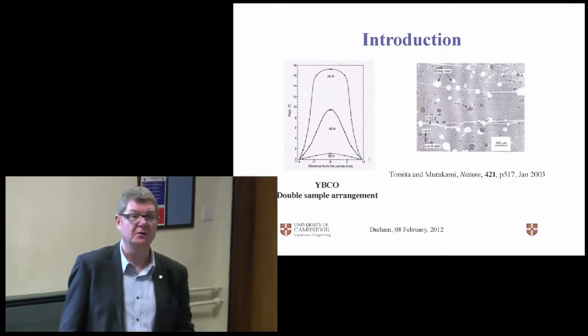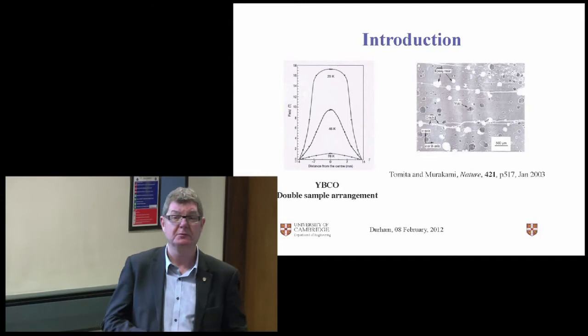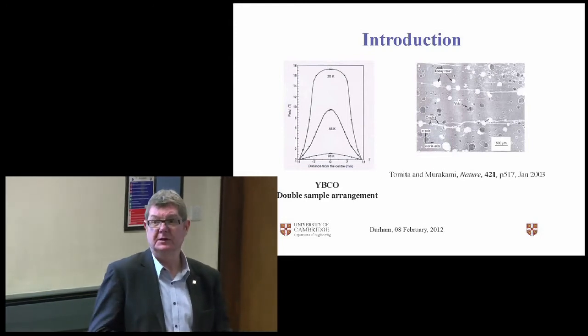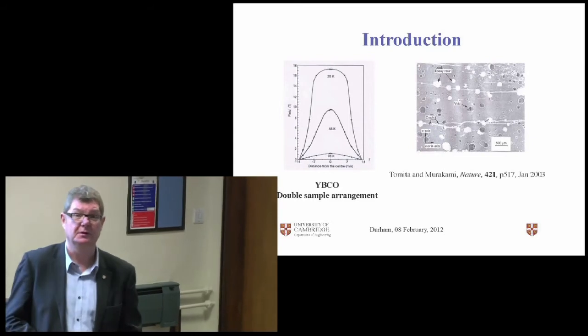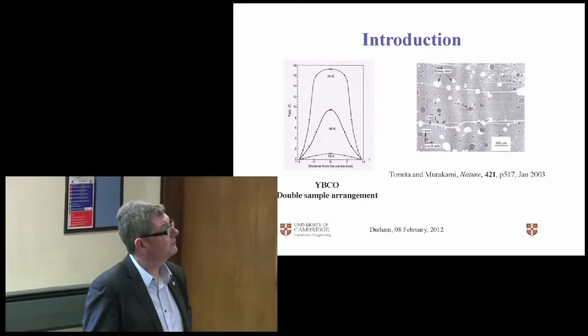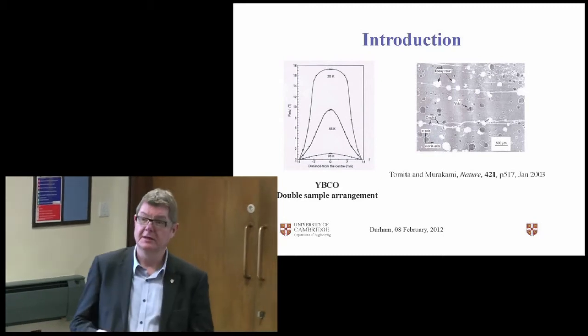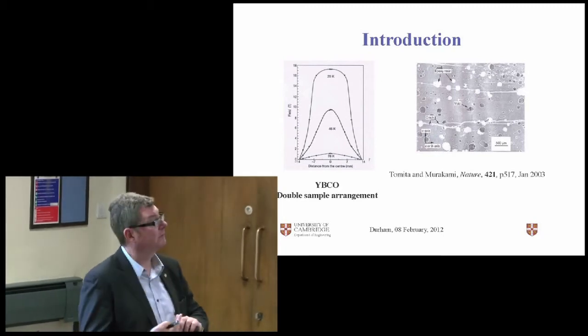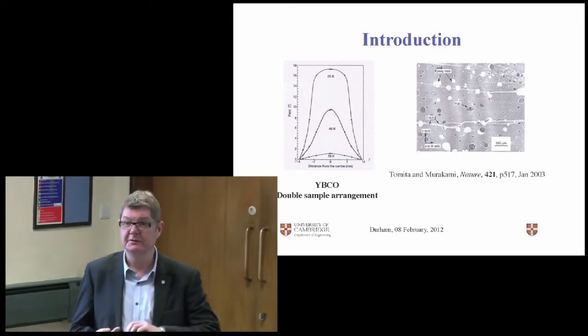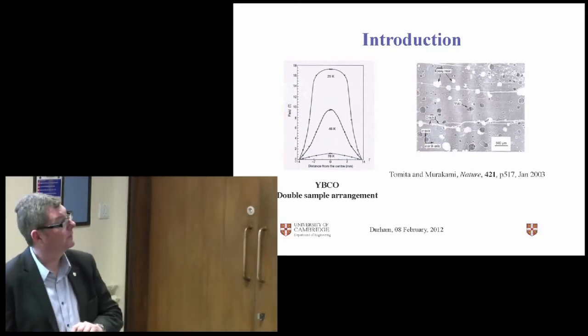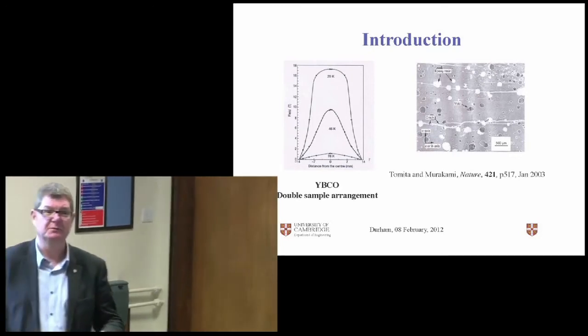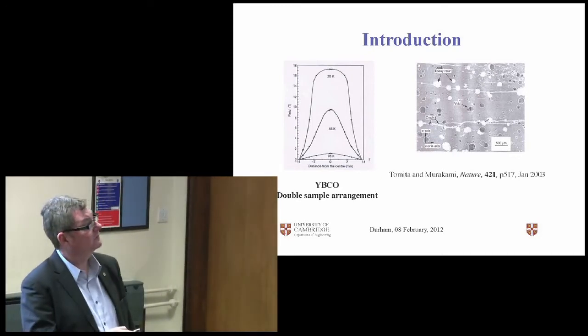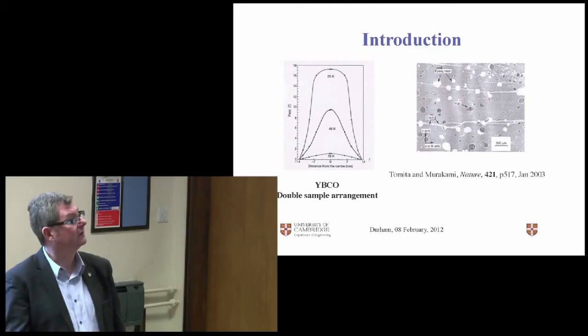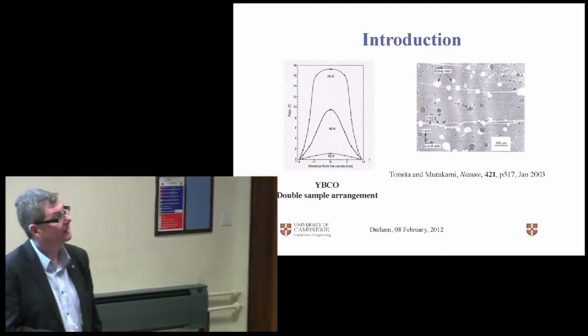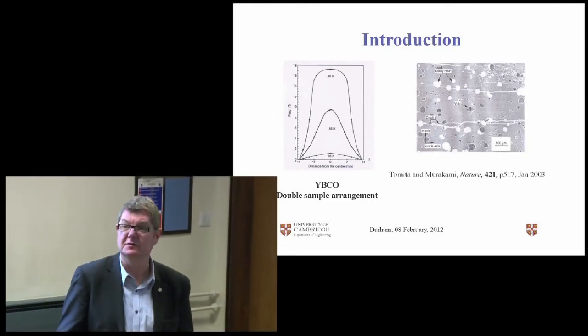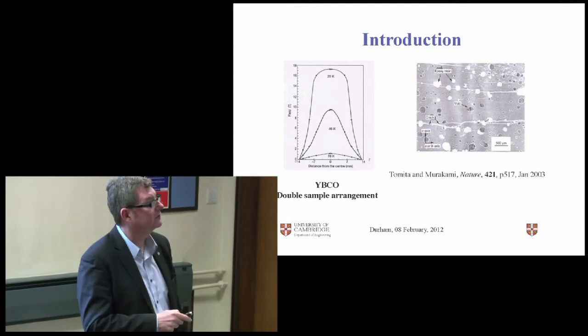And the energy density goes as field squared of two magnets repelling one another, or in fact, the energy density is stored in a given magnetic field. So neodymium-iron-boron will generate a Tesla. There's a documented incident of a technician in the US getting his finger caught between two neodymium-iron-boron magnets coming together, and they took the end of his finger off. That's 1 Tesla. And we talked about iron, and that was a maximum of 1.7 Tesla. So 17 Tesla is 10 times the field of iron, which is 100 times the energy density. And of neodymium-iron-boron, it's about 400 times the energy density. So this is a serious amount of energy.